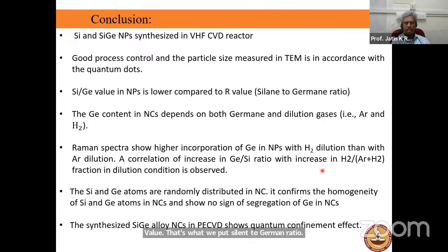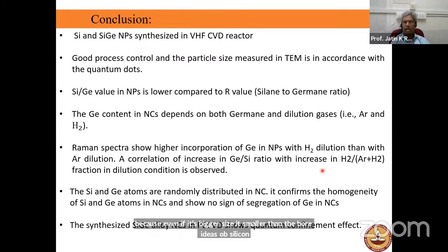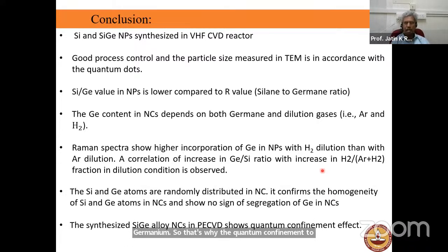But the most important thing is that the band gap shows the quantum confinement effect, and they are all quantum dots. You must realize that the quantum dot size of silicon is only 5 nanometer, germanium is 24 nanometer. So silicon germanium can easily be made into quantum dots, because even if it's a bigger size, it's smaller than the Bohr radius of silicon germanium. That's why the quantum confinement effect comes in silicon germanium alloy nanoparticles, even at bigger sizes.